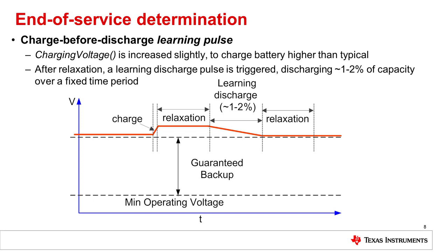In a charge-before-discharge pulse, this is primarily used in a system where you have a programmable charger, so you can actually change the charging voltage. Long-term, the battery may stay charged at a level a little below the maximum allowed — say 4.0V. When a learning pulse is triggered, the system will charge to a slightly higher voltage, say 4.2V. It terminates charge, and then there's a relaxation period where the cell voltage stabilizes to DC levels, and then we turn on our learning discharge — a controlled discharge of on the order of one or two percent of capacity. This turns off, and then we relax again so that the voltage stabilizes to a very settled level.